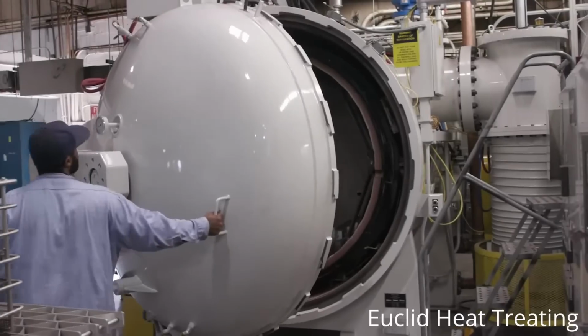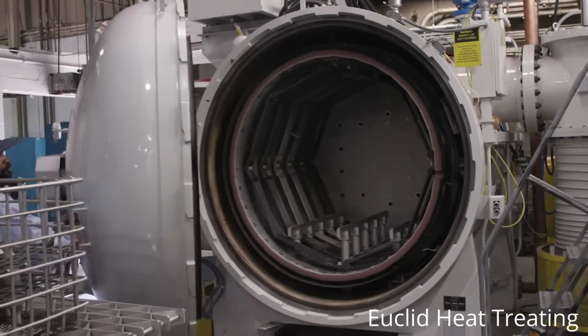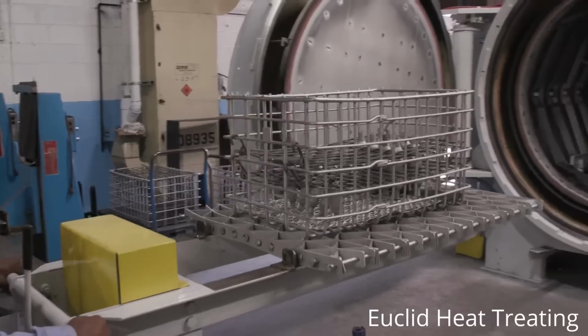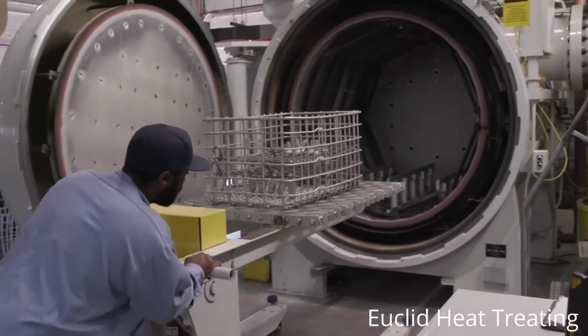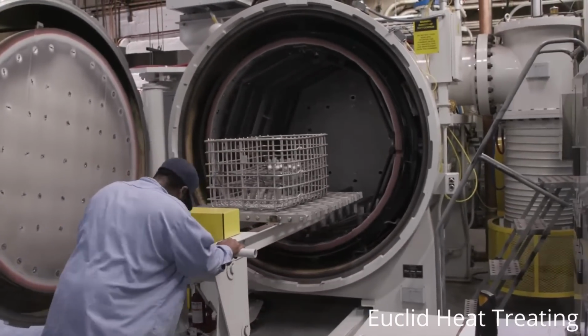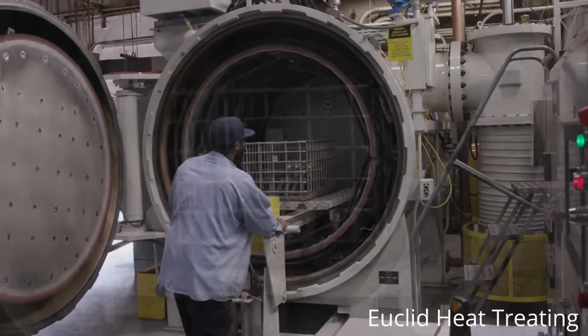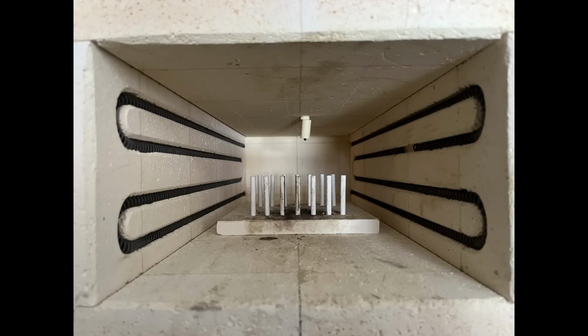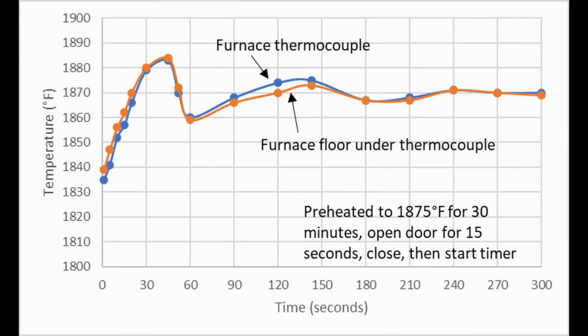There are pros and cons to both situations apart from the number of knives. A furnace is not perfectly evenly heated. It's going to be slightly colder at the door or in the corners, and there's some kind of thermal gradient between those hot and cold spots. There is a control thermocouple that measures the temperature, and the furnace is constantly adjusting to hit the target temperature. If you're heat treating one knife at a time and that knife is right next to the thermocouple, you can be reasonably sure the temperature the knife sees is very close to what the thermocouple is measuring.